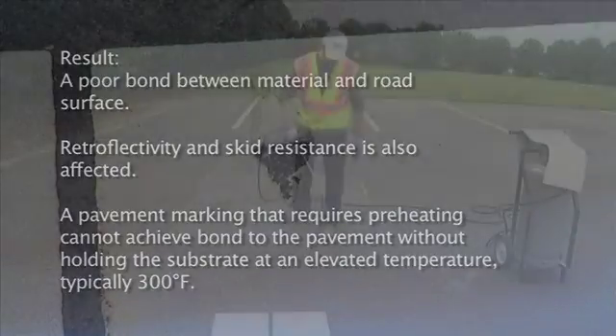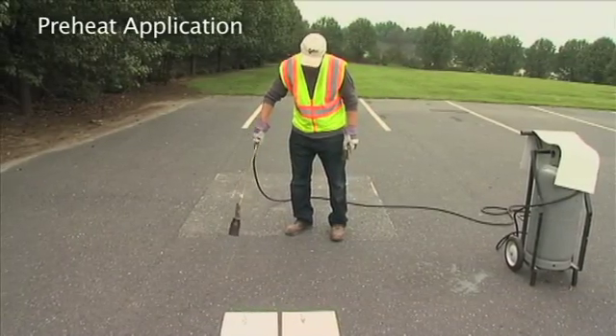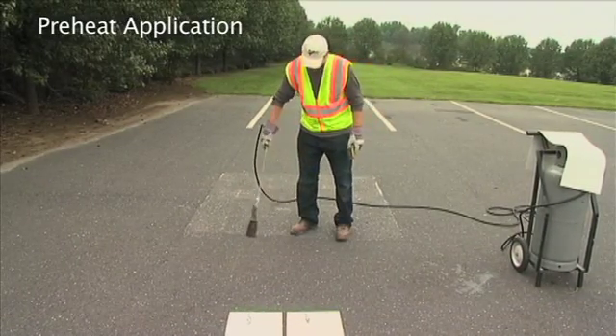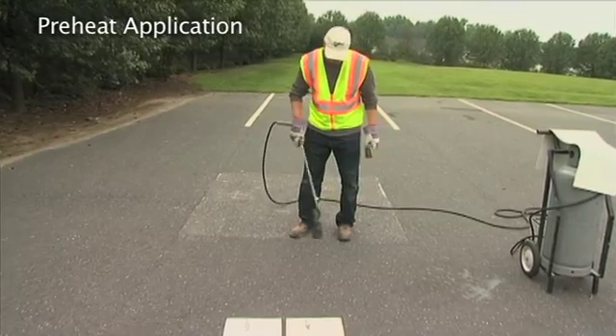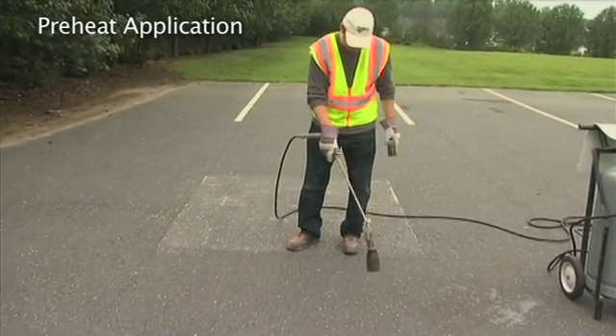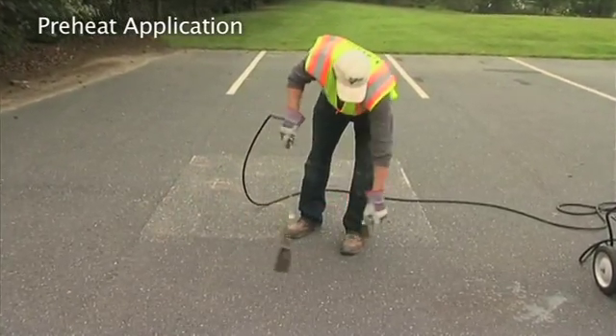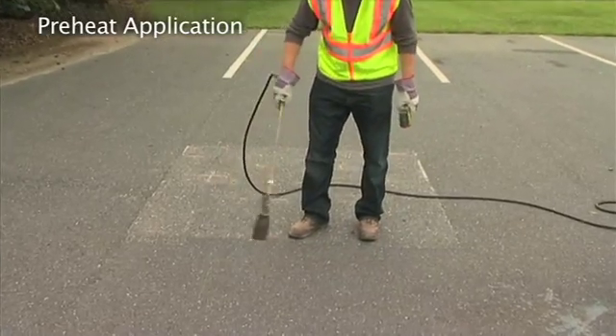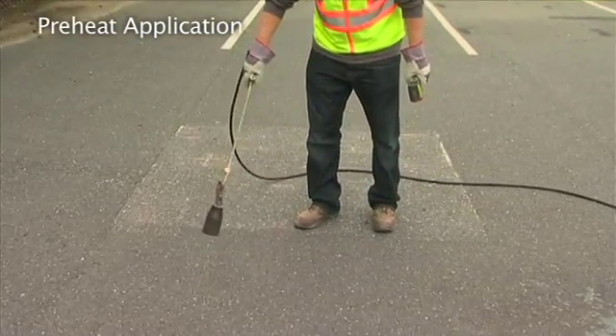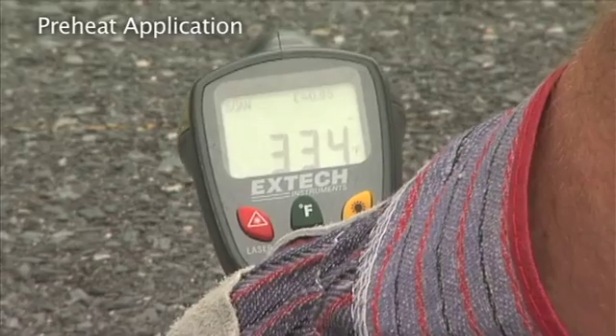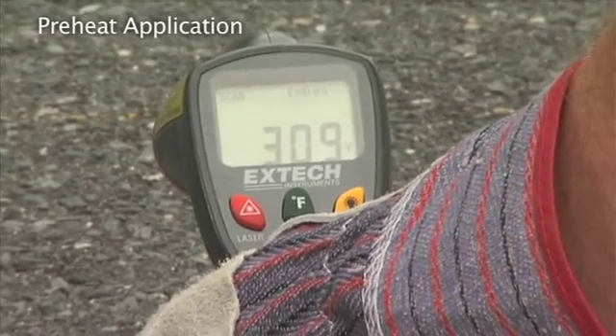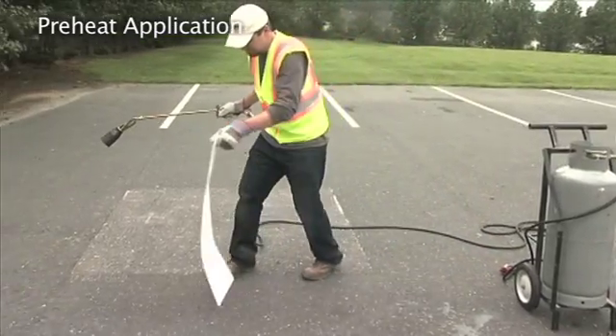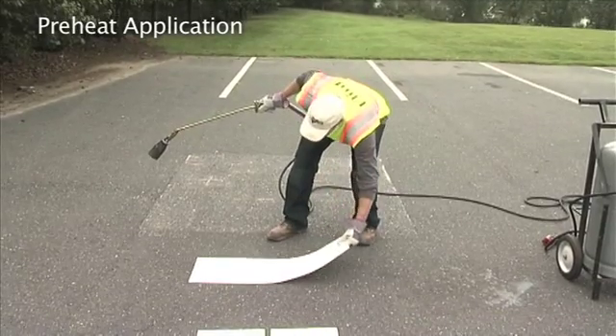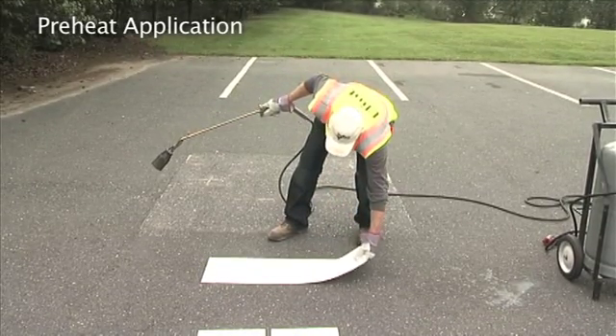We'll demonstrate that now. Starting with a clean surface free of debris, we have chalked a section of 12 inches by 3 feet to apply the preheat product based on the manufacturer's application instructions. Using a magnum heat torch at maximum output, which is best suited for preheating the surface, the pavement is preheated to at least 300 degrees Fahrenheit. Once the surface temperature is above 300, the material is immediately placed on the surface.